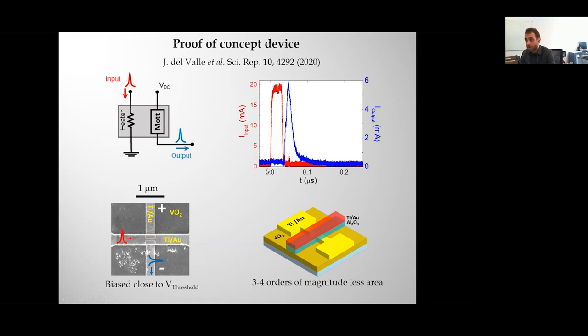And this is actually what you see here. This is the current as a function of time. In red, you have the input current represented in this axis, and in blue, this axis, this is the output current of your device. We send a pulse to the device, and you see that we can make our device spike. So you have spike in, spike out, which is what a neuron should be doing. Importantly, this is current that our device is outputting through this electrode. So it's an active device.